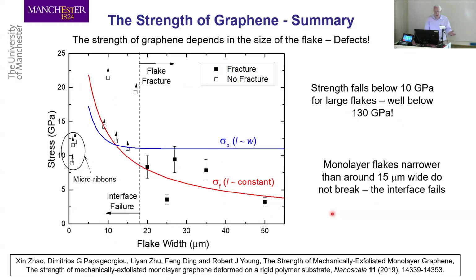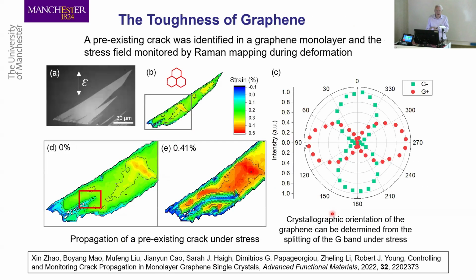And of course, the experiment that was done originally was under a point indenter where we had a very small area of deformation. So we have this interesting size effect and find that the large flakes are much weaker than reported. So that's the strength. Now we want to look at toughness, because as well as strength, toughness is important, and it's not the same as strength. Toughness is propagating a crack, where strength is sort of initiating a crack.